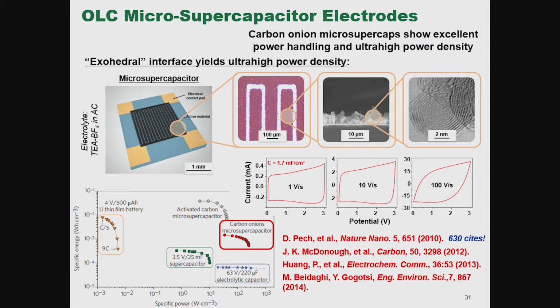Here's a Ragone plot of some typical micro-devices. Here's a lithium thin film battery, very high energy density but not very high power density. But electrodes like this, fabricated from activated carbon and carbon onions, give both high energy and power density, with the carbon onions giving even higher power density. In other words, that open architecture and those curved surfaces really enhance the power output as well as boosting the energy output.